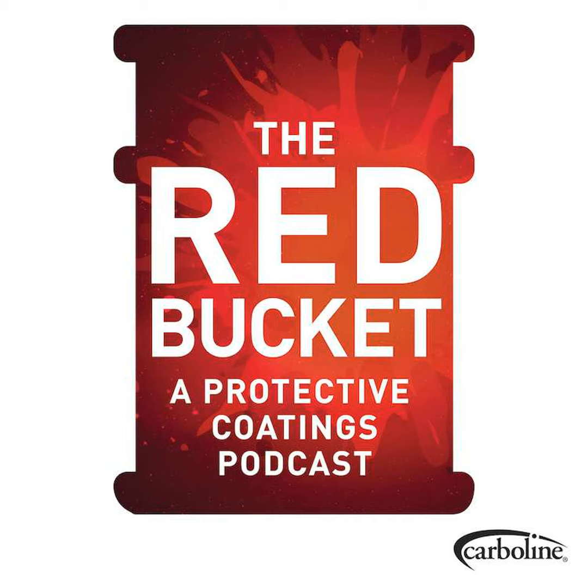Well, and what does profile mean? Well, we hope to remove the laitance. That's one of the things it means. Yeah. And we hope that it removes any impurities left on the surface, which could be part of the laitance. But we also hope it gives us a roughened surface so that we can have good surface area to bond to. But with all that in mind, if the concrete doesn't meet the physical properties, we know that the coefficient of thermal expansion of concrete versus coatings is totally different. Yep.